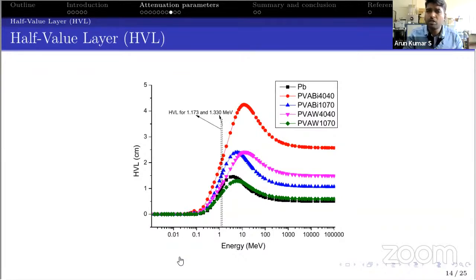Why? Then only can we use this material for real life applications. Here, one more thing we need to notice is that these PVA hydrogel films are flexible and stretchable. So if we can get a thinner material, with the lowest half value layer, it can become a potentially promising material for the future. And here I have mentioned the half value layer for the conventional cobalt-60 energy range, that is 1.173 MeV and 1.33 MeV.